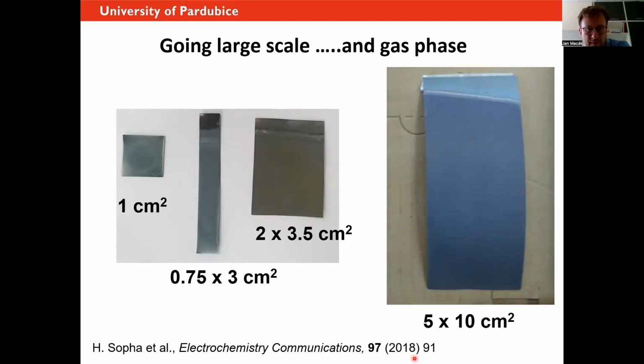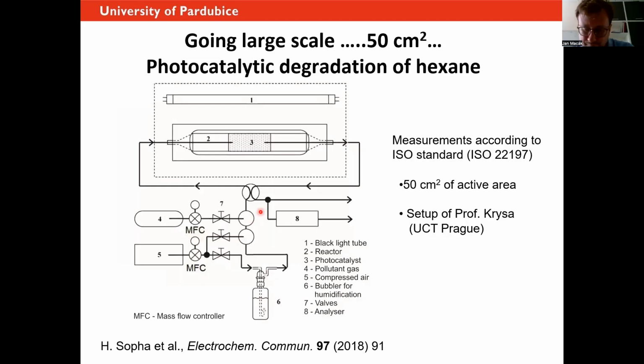So about 4 years ago, we were able to achieve, by proper management of the anodization, so cooling of the electrolyte, and using the right electrolyte also, to grow 50 square centimeters. This was at that time the record. And we are trying to beat it ourselves, and we can now make these nanotube layers on 50 square centimeters. This opens the door for completely different types of experiments that would not be possible at the small scale. And that is using some ISO standardized measurements, because we have now 50 square centimeters, so we can really go on and put these layers into